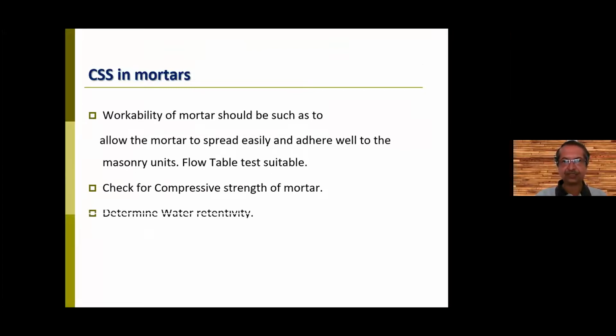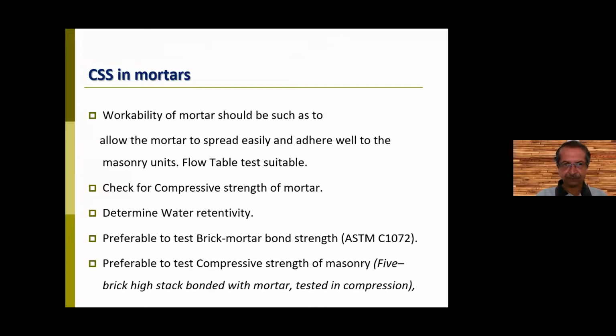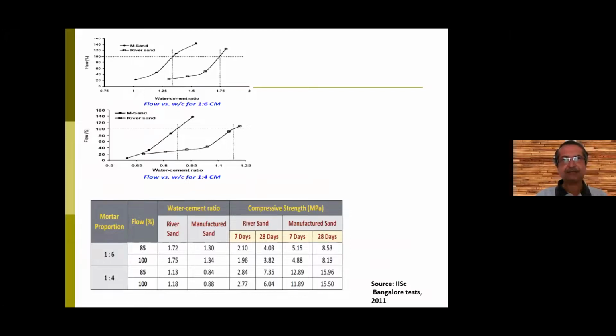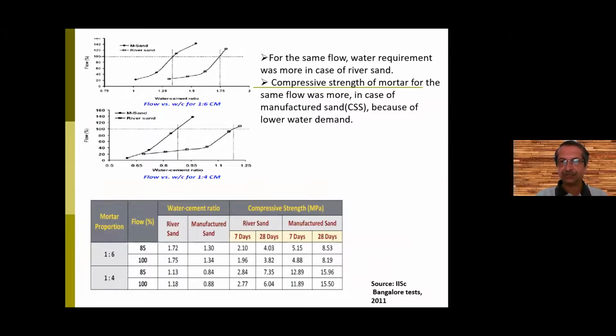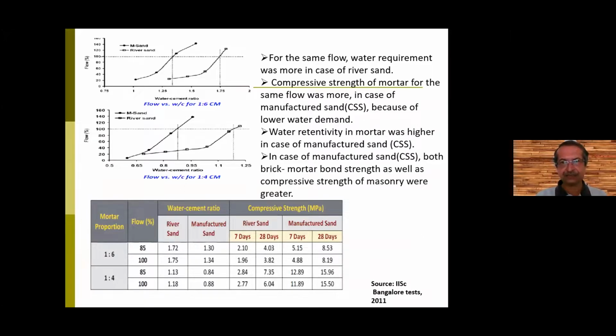So check the compressive strength of mortar before using, determine the water retentivity, and also, if possible, test the brick mortar bond strength. So it's preferable to test compressive strength of masonry, that is using a 5 brick high stack bond with mortar testing compression. Again, we got some tests done in Indian Institute of Science for mortar. We found that for the same flow, water requirement was more in case of river sand. Compressive strength of mortar for the same flow was more in case of manufactured sand, and water retentivity of mortar was higher in case of manufactured sand.